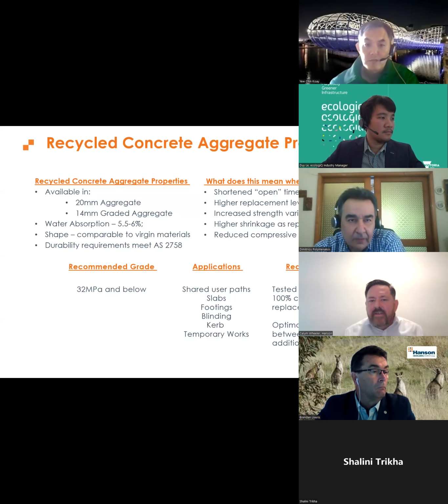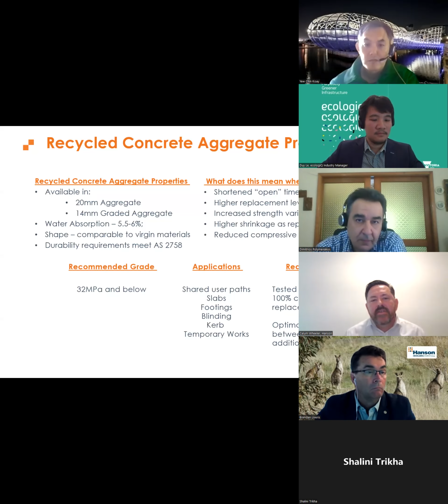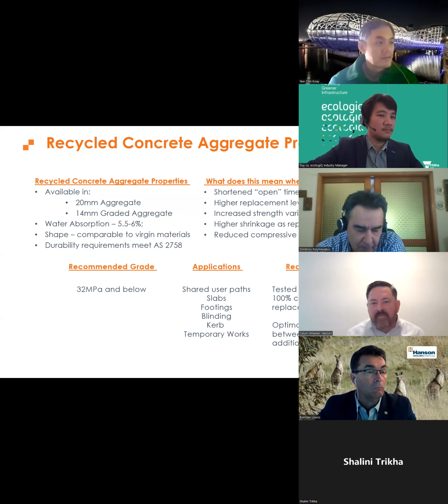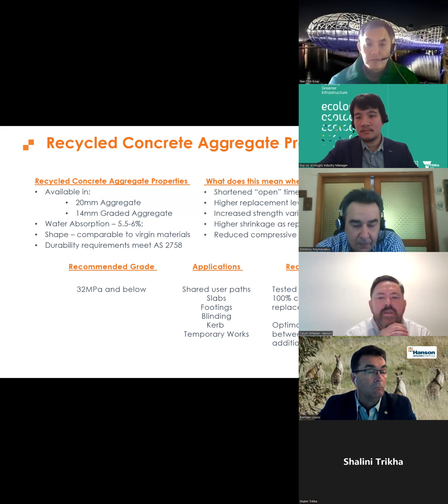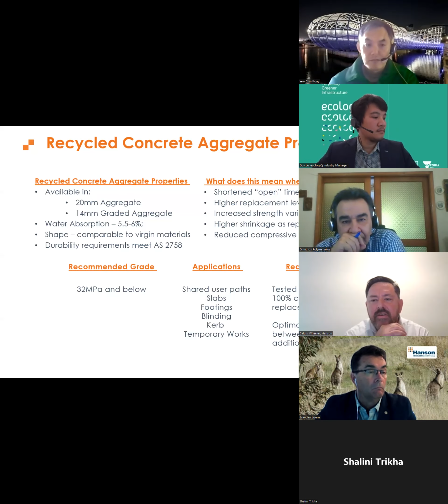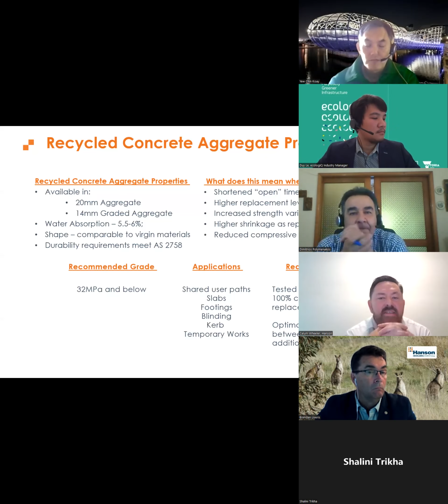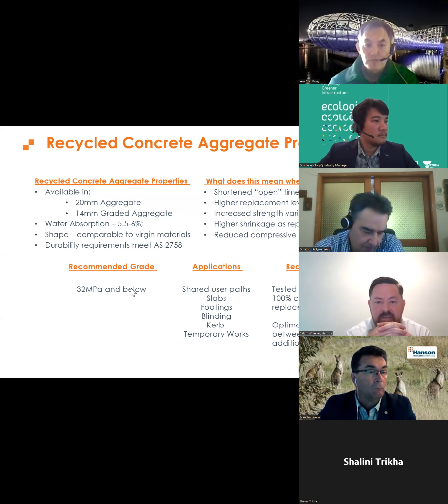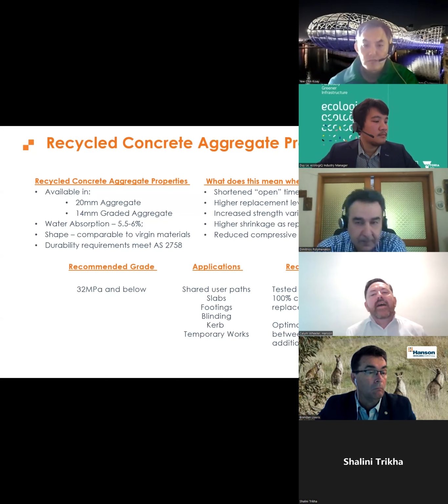So what we found is that we recommend that it is a usable product, but it does have some limitations. We think that it should be around the 32 MPa and below. There's plenty of applications that this product can be used in. And when we've taken it out to the field, we've looked at replacement levels between 10 and 100% of the coarse aggregates. What we've found is the optimal replacement levels sit between around 30 and 50%, and that's to mitigate or eliminate the additional cement offsets. That's why we've come up with those.